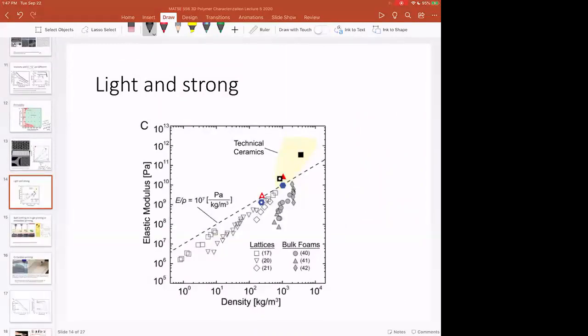And they put their results on this plot where if you plot the elastic modulus or some kind of mechanical property versus density, this type of plot is called an Ashby plot or an Ashby type plot. And you see that if you want very strong materials, in essence, you have to go to high density. So 1,000 kilograms per meter cubed or 10,000 kilograms per meter cubed is getting very heavy. But you can get very strong materials. And up here we have technical ceramics. So these are high strength ceramics that they make CMCs out of. So ceramic matrix composites. So this is like silicon carbide and other things like that.